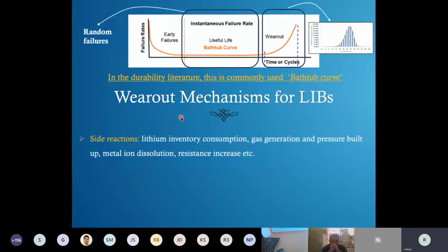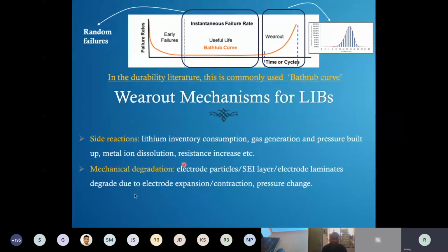So they can be classified in two major categories. One is side reactions. There are side reactions happening within the cell, which basically eat away the lithium inventory. It also results in gas generation, pressure buildup, or metal ion dissolution, resistance increase. So all these side reactions. And then the second part is mechanical degradation, where the electrode particles or the SEI layer or the electrode laminates degrade due to electrode expansion and contraction. So we will look into all of these in the coming slides.